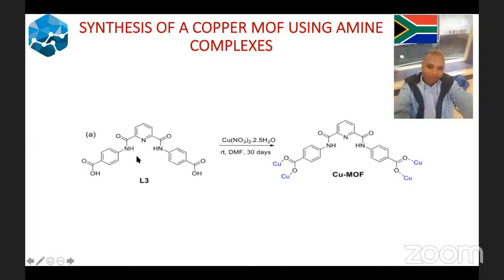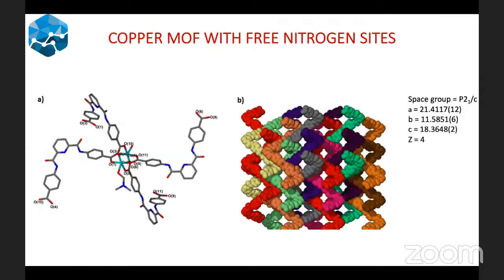Why pincer complexes? Because pincer complexes in literature have been shown to be highly active towards hydrogenation of carbon dioxide. For example, your ruthenium or your palladium can be inserted there, and then of course you can carry out your catalysis. So after 30 days, Spelele managed to isolate the MOF, and of course we ran the single crystal diffractometer, and this is what we got.